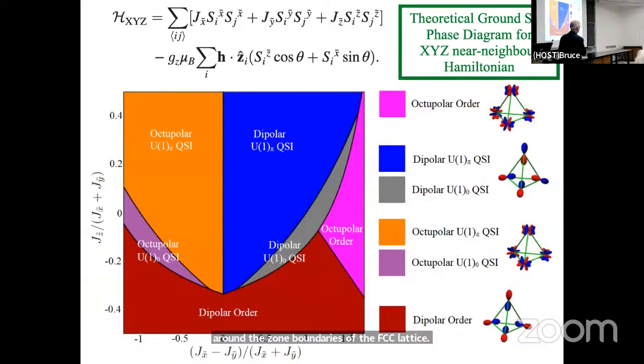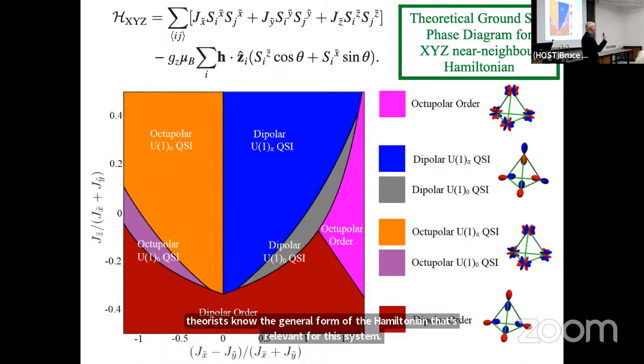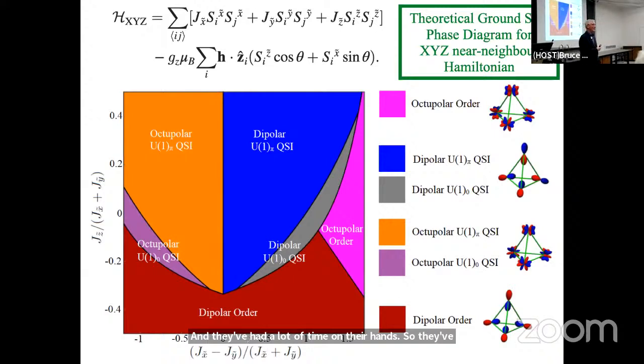So the theorists know the general form of the Hamiltonian that's relevant for this system, and they've had a lot of time on their hands. So they've actually worked out all of the possible phases that you can get from this problem, at least that are theoretically expected. Okay, and there's quite a few phases here. But what I really want you to pay attention to is how much of this phase diagram is occupied by states that are labeled QSI. So QSI is a quantum disordered quantum spin ice. And there's actually 4 different flavors of it. There's something called a pi flux quantum spin ice. There's zero flux quantum spin ice. I can describe those to you if you like in, say, a question. I'm not going to do so right now. Okay, but these are 2 different flavors of quantum spin ice, and they can be dominated either by the dipolar degrees of freedom or the octupolar degrees of freedom.